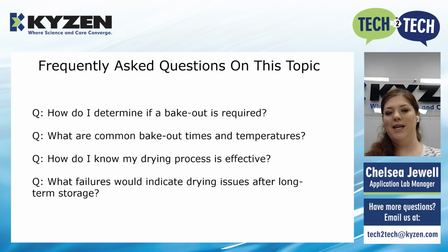Another thing we see is very, very complex components. You're making sure they're dried out, which is super critical. Those are the things we tend to look for in a post-process bakeout. As far as bakeout times and temperatures, it really depends on what materials you have on your board. If we're talking about copper, you don't want to take it to extreme temperatures because that can induce oxidation on the surface, which inhibits other post-processing steps.